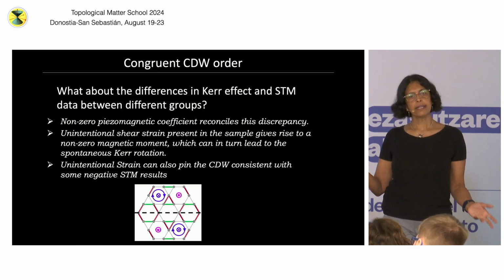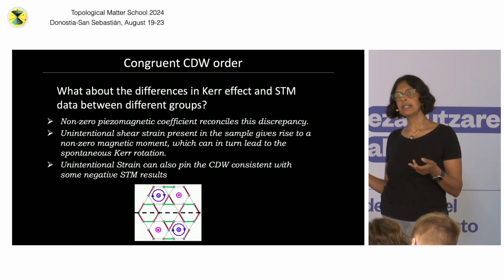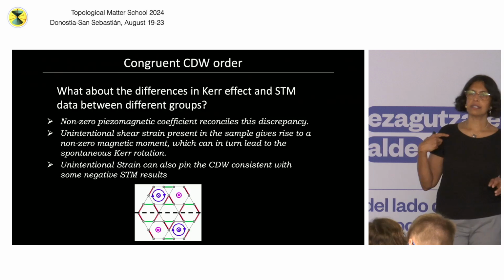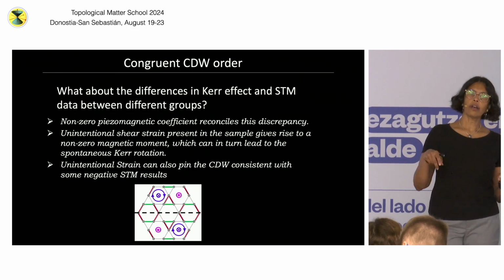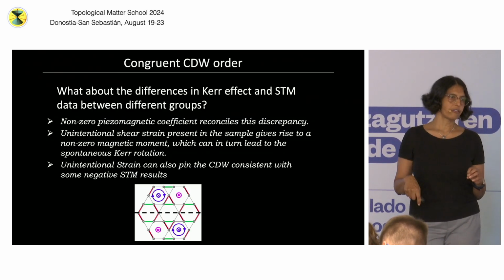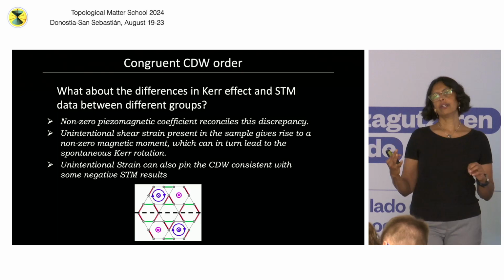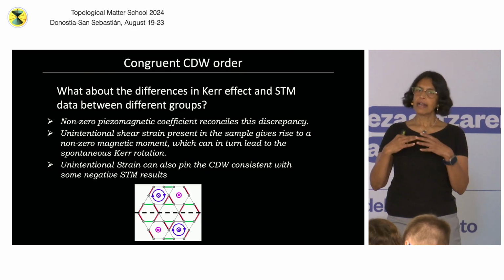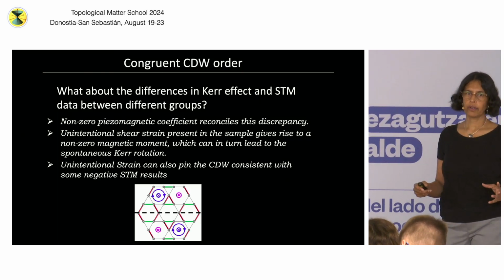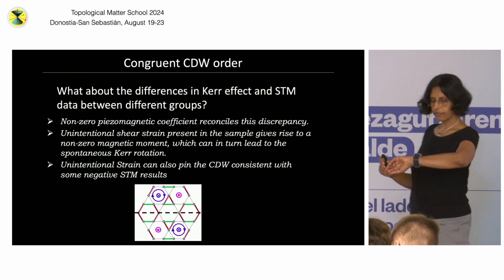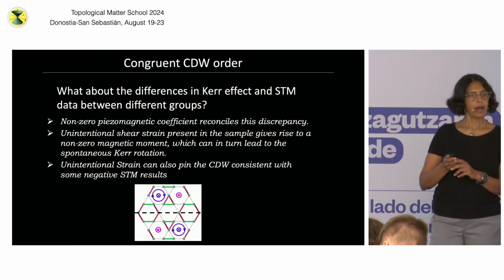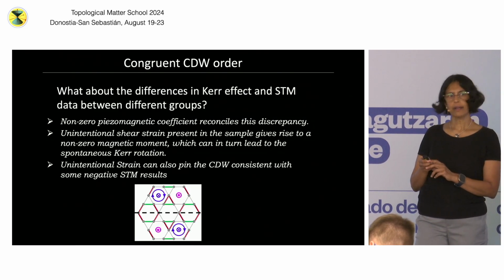Same with the STM. If you happen to have a particularly strained sample, and we actually do see this ourselves, you will not see this reversal with a magnetic field. So the sample is extremely susceptible to strain, and time reversal symmetry is indeed broken. Okay, so that's it for the first part of the talk. Shall I just keep going? Yes?